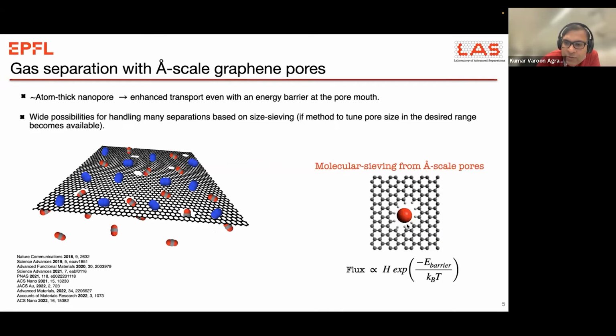But the idea is, once the hole size is comparable to the size of the molecule, when the molecule goes and interacts with the hole, or wants to go across the hole, it feels the interaction from the edge of the pore. That interaction is then accounted as an energy barrier to cross over the pore. The larger the molecule, the larger the energy barrier, and this energy barrier is related to the flux of the gas through transition state theory. A larger energy barrier leads to much lower flux. And so based on this energy barrier, you can have selectivity between gas molecules.